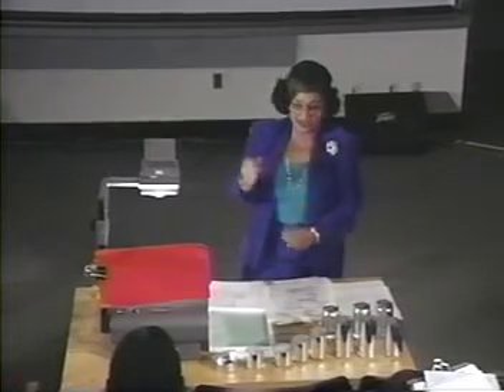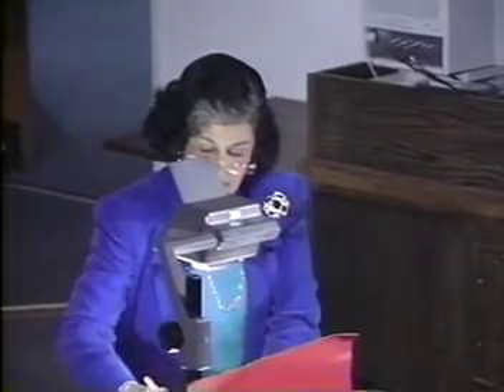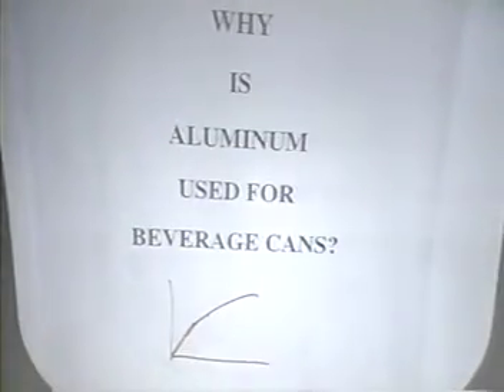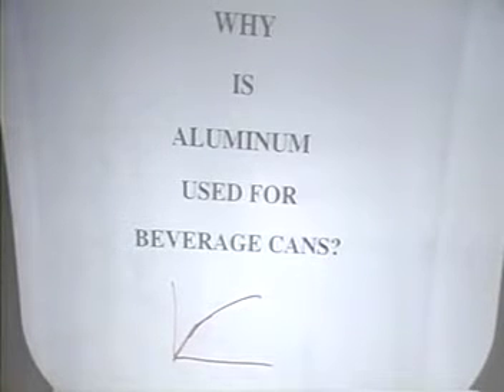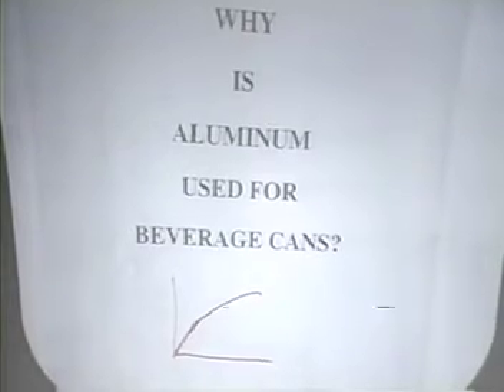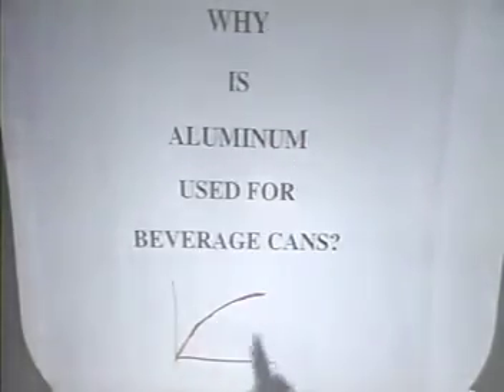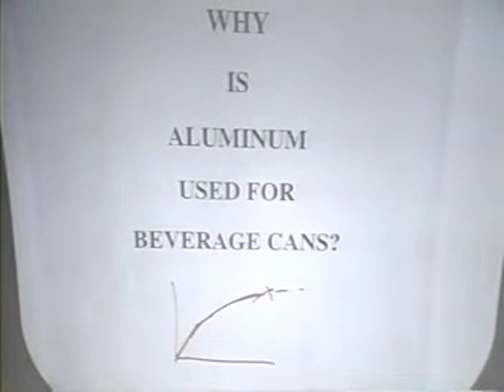Okay, and what that means is that any defects that are created in the microstructure as a result of stressing it, and that's all this is doing. All this is doing is stressing the material. That's why when you see the stress strain curve, it goes up like this. Continuous increase in stress to keep deformation going. We're actually changing the microstructure, creating little defects. And the question that he asked is that these little defects would tend to make it harder and harder to deform the material, which it is. It also tends to shorten the time to fracture.